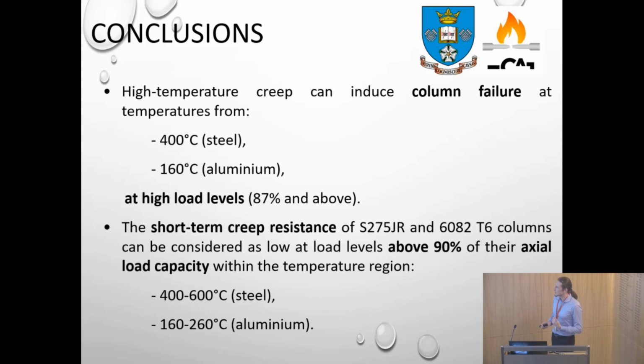A couple of conclusions. As you've seen from the tests themselves, there is induction of the column failure at 400 degrees for steel and 160 for aluminium. That's been obtained by tests. This happens at high load levels, so there is a certain probability of failure of columns if the load level in the column is high. So you have to define some kind of a temporal resistance of the column at those load levels.